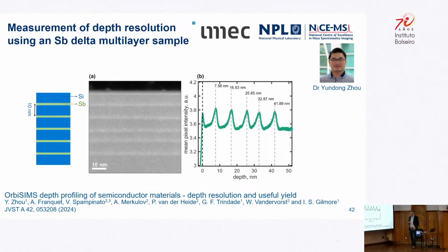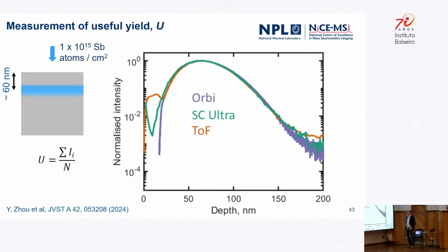So we were really interested then in better understanding how we could improve the technology for the semiconductor community. So in a collaboration with IMEC, we looked at a standard sample, which is antimony delta layers in a silicon matrix. So this is work of Yundong Zhou in my group. This is a depth profile now, so we're going down in depth to a few hundred nanometers, and we're measuring now the amount of antimony atoms that have been implanted in a silicon wafer.